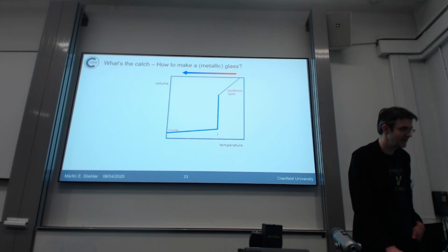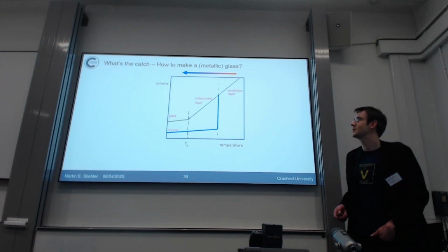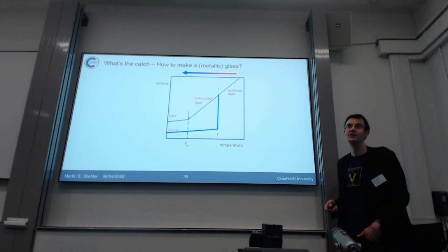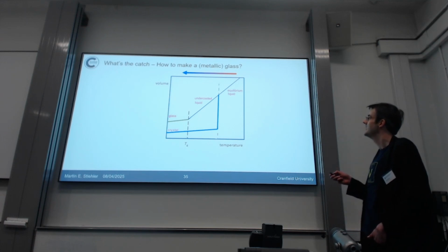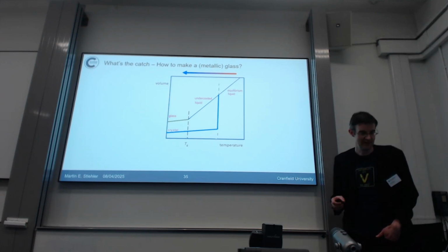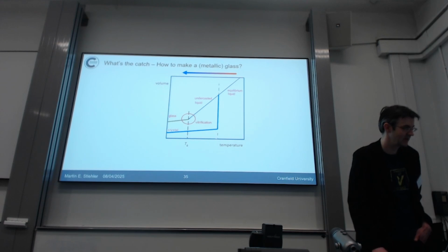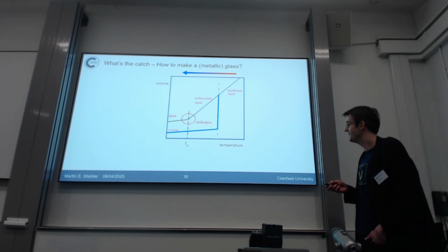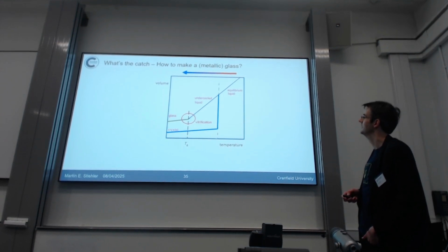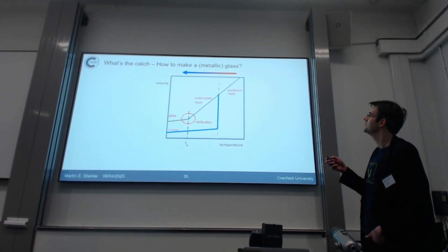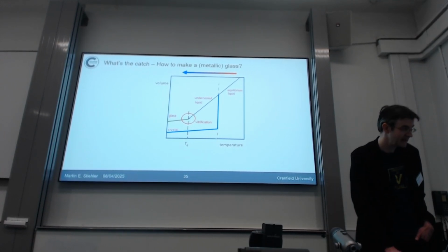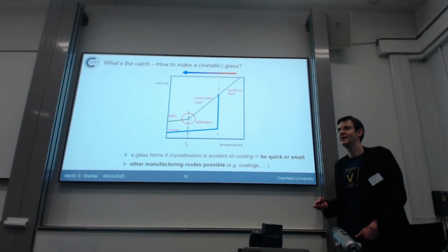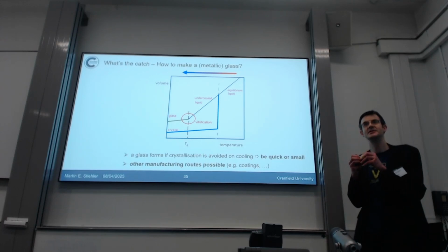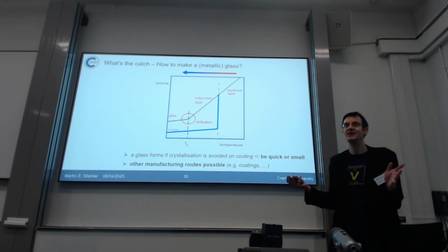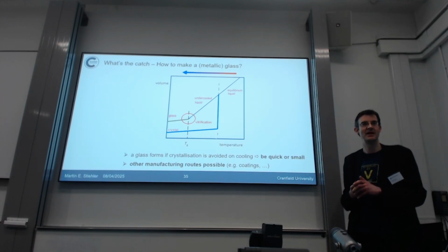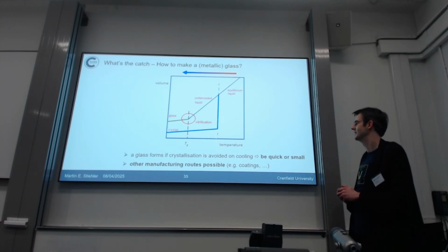But if you do it correctly, or if you do it very quickly, you can considerably undercool your liquid way below the melting point of the liquid, and at some point the material turns into glass. We call this vitrification, and the temperature here is also called glass transition temperature. And in order to do this, you either need to be very quick, as I said, or you have a limitation in size. The smaller the piece is, the easier it is for the heat to get out, and this is where the size limitation comes in, which I mentioned right in the beginning.